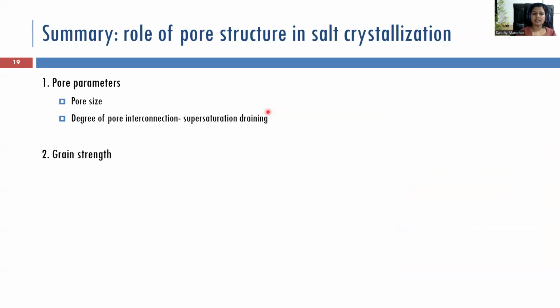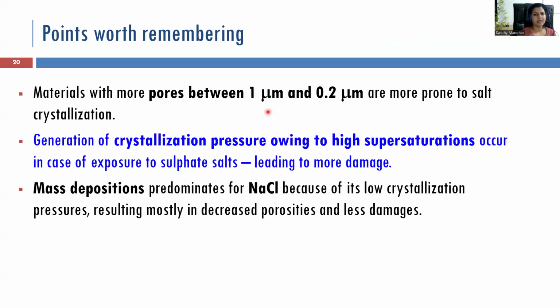Now the last factor is the grain strength. Even if everything supports crystallization and formation of pressure, if the pressure generated, which creates hoop stress, is lower than the tensile strength of your material, then again you will not have damage. So if the material's grain strength is higher than the crystallization pressure, you will not have any damage in the system.